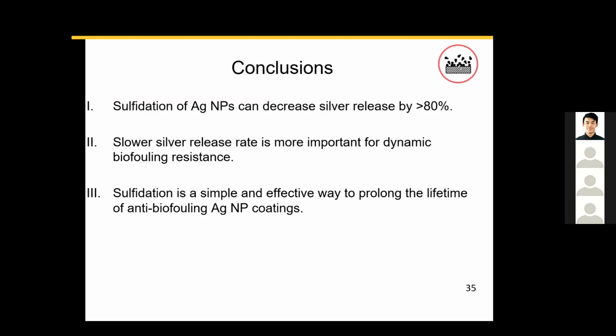So from this project, we have concluded that sulfidation can decrease the silver release by over 80%. And we know that a slower silver release rate is more important for dynamic biofouling resistance. This is because we want a constant but slow release of silver ions to remove biofilms more efficiently in a reverse osmosis module. Also, something I wanted to highlight is that sulfidation is a simple and yet effective way to prolong the lifetime of anti-biofouling coatings.